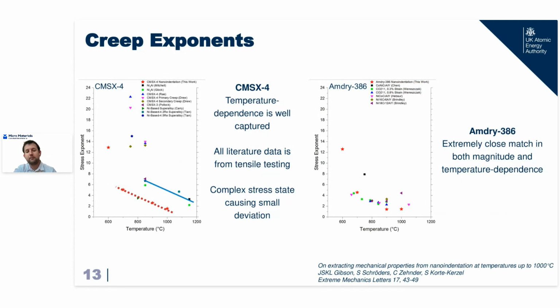For our fine polycrystalline bond coat, that's most likely why we get this much closer match in both the magnitude and temperature dependence of our creep stress exponents in our nickel bond coat, which is very good. It means we can then move on to materials development and really understand that the sorts of creep exponents that we're getting at these temperatures might actually be relevant for application design as well.